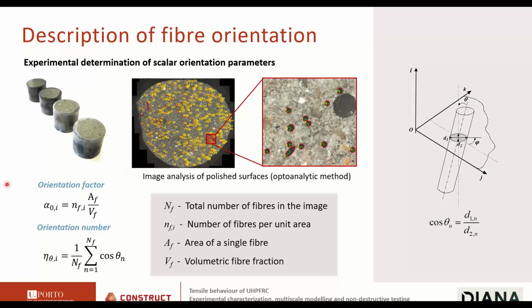Okay, so it can be shown that the fiber orientation factor that we will use throughout this presentation can be obtained through this very simple equation. The fiber orientation factor in this surface is the number of fibers per unit area, times the cross-sectional area of one fiber, divided by the volumetric fiber fraction. Okay, so if you multiply alpha 0 by the volumetric fiber fraction, you have the area of steel per unit area of composite.